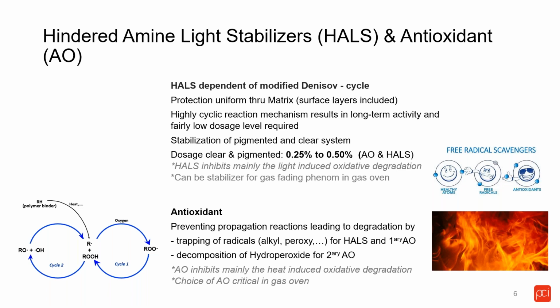Now, in regards to the amine light stabilizer and the antioxidant, those two are the heat stabilizer, if you prefer, even though the amine light stabilizer is mainly here as a light stabilizer, with a synergistic effect with the UVA. So the UVA filter is our number one mechanism to protect the coatings, and then synergistically with it, we use an amine light stabilizer that pretty much performs following the Denisov cycle, and that is actually trapping radicals that are formed during the degradation process of the coatings. Very similarly to an antioxidant. The main difference is obviously an antioxidant is used as a heat stabilizer, where the amine light stabilizer is primarily used as a light stabilizer.